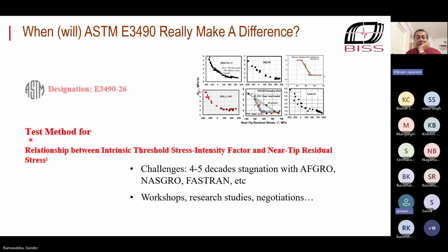From the way we are working here for Airbus, whatever the effect of the crack closure is, it is considered that when you have a negative loading, practically there would be no crack growth, but due to the conservatism, the compressive effect is ignored. But still it will have an effect. So I guess this standard which is being developed could throw more light on such aspects, I believe.